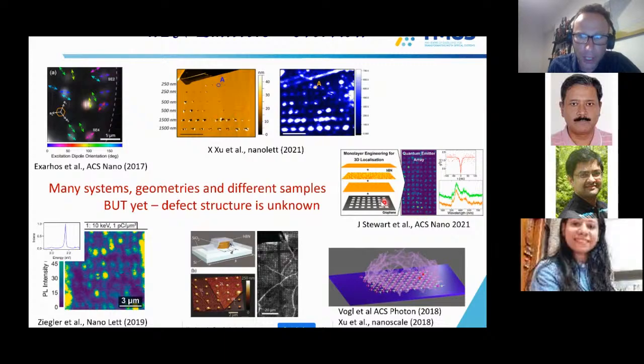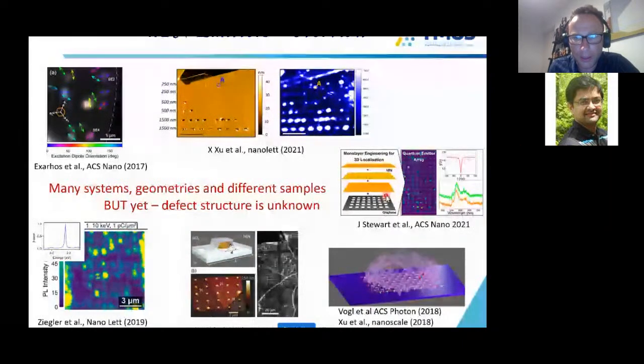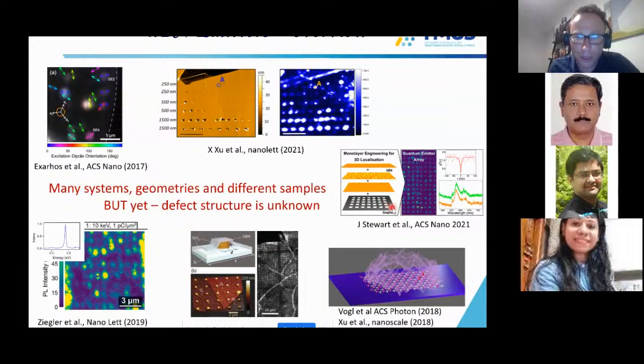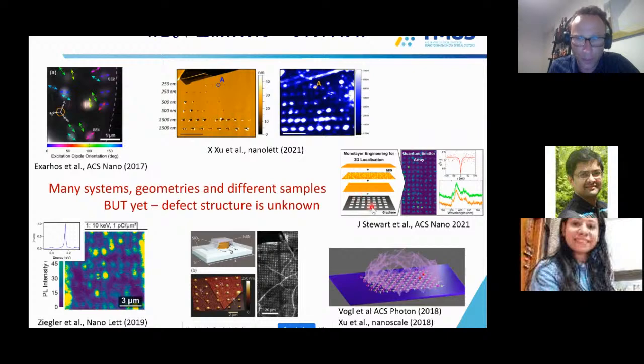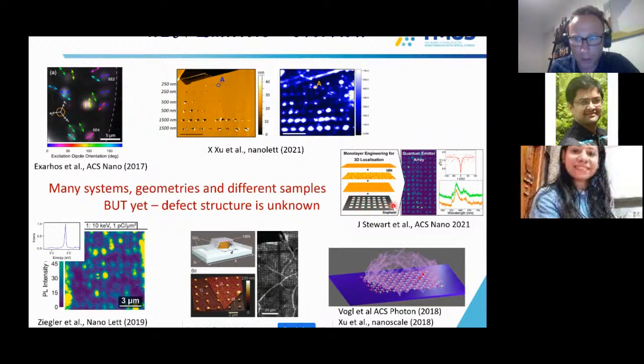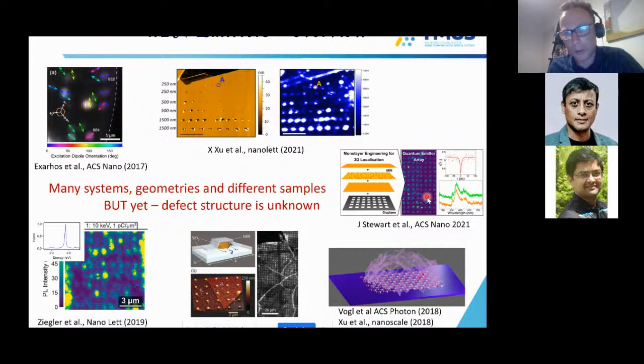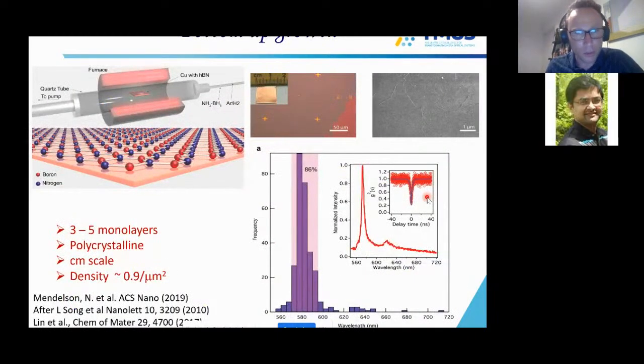So they made an array of hBN emitters, and they did it by basically taking an hBN flake with a very high density of emitters. You can see them here. And then encapsulating it with pristine hBN and patterning graphene. And because graphene induces non-radiative energy transfer, essentially you're killing the emitters everywhere where there is no aperture. And everywhere where there is an aperture, you basically have an emitter, and you can see it here. And some of them are, of course, single photon sources. So you can see this beautiful emission engineering is possible purely because you're working with these atomically thin layers of boron nitride. So one question remains unknown, and this is, of course, what is the source of this boron nitride?